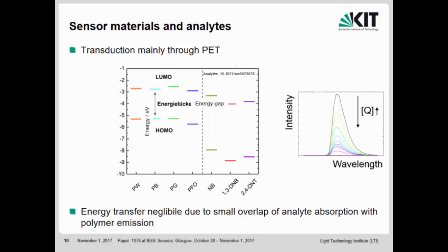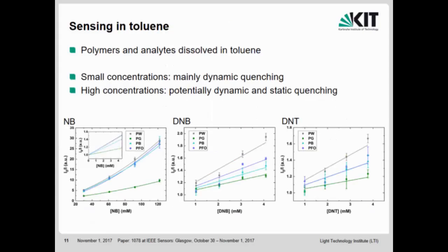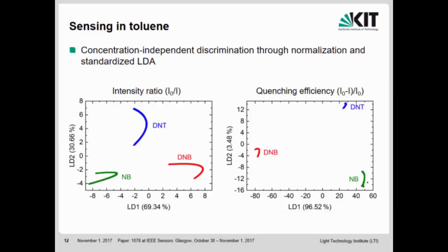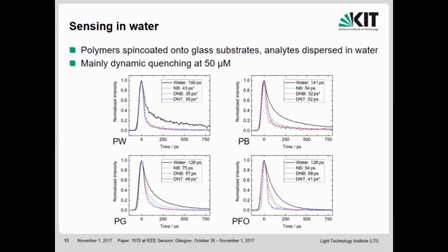And what else did we observe? We could also prove that there is no shift in the emission of all these materials, which is also important. Then we measured in toluene, and for different concentrations, we could figure out that this will in principle work completely in solution. Then we did a linear discriminant analysis to see if we can later also discriminate between these materials. So this also works out. And then we went over to water. We spin coated the polymers onto a glass substrate and could measure the lifetime within water, and see that we have a dynamic quenching process. Some of them are even below the detection limit of the measurement system, but in principle we could prove that we have the dynamic quenching.